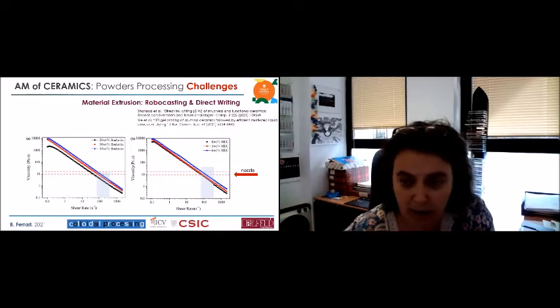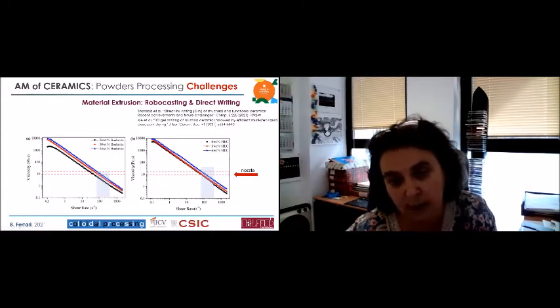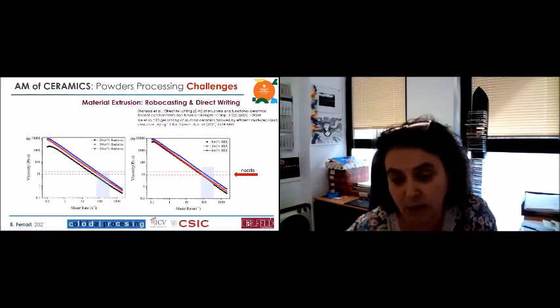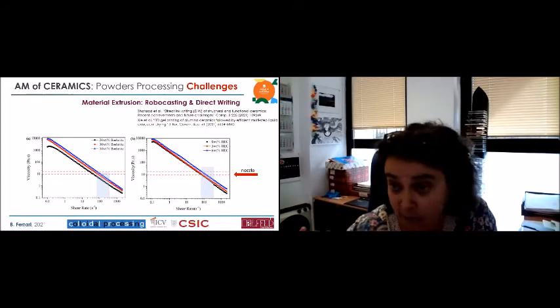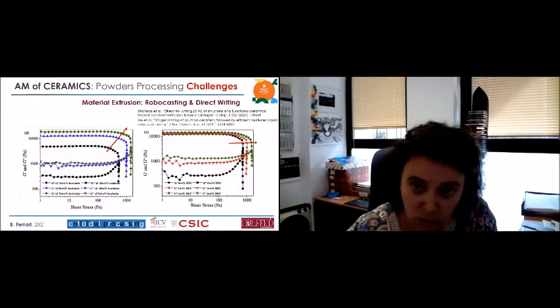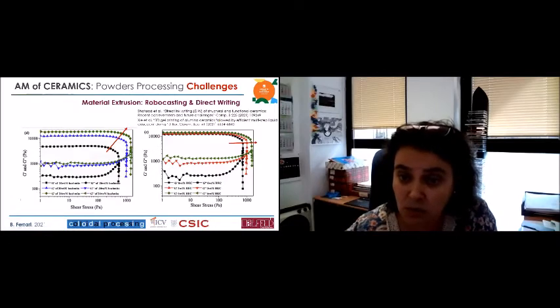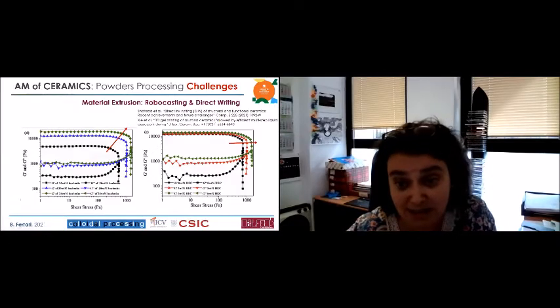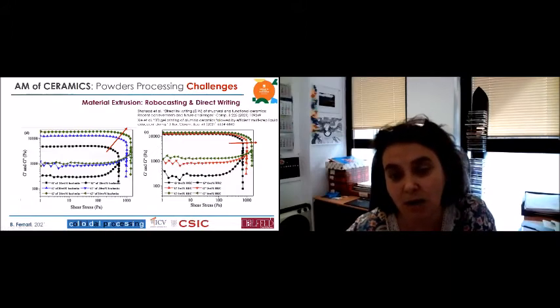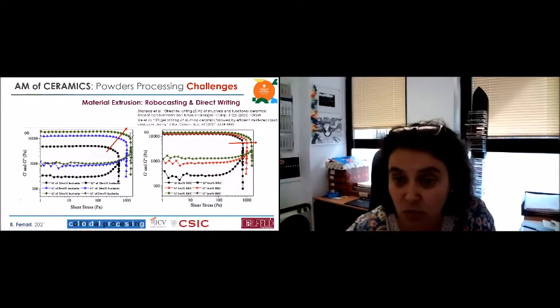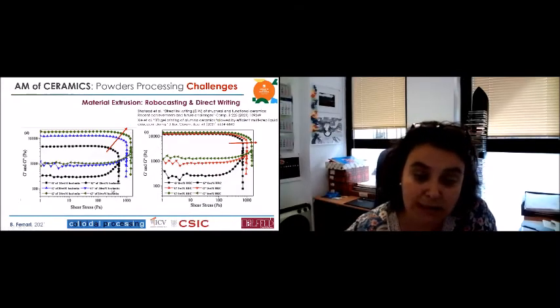And what we look for here is the shear rate that you promote in the suspension, in the ink, when the ink is passing through the nozzle, right? It's very important to have this kind of viscosity, not too high, not too low, to make the ink pass through the nozzle with light pressure on your syringe that you use to print. But it's also very important to know how this ink behaves in the solid state, right? How stable is the solid state that you have with the gel that you include inside of the ink.